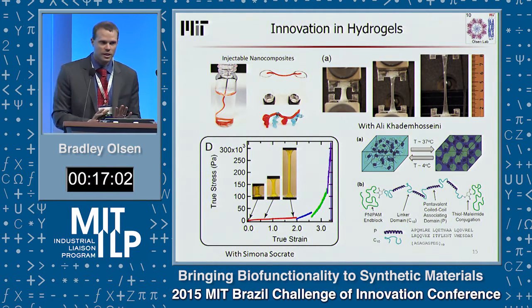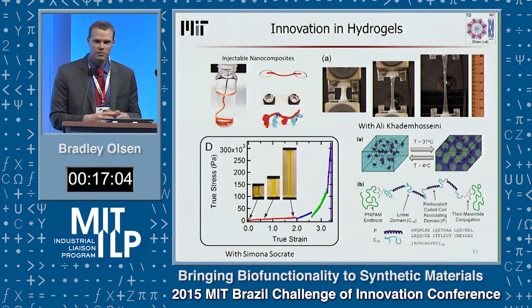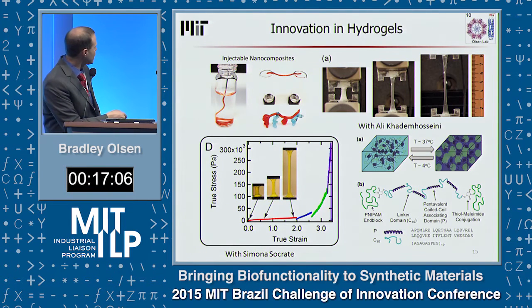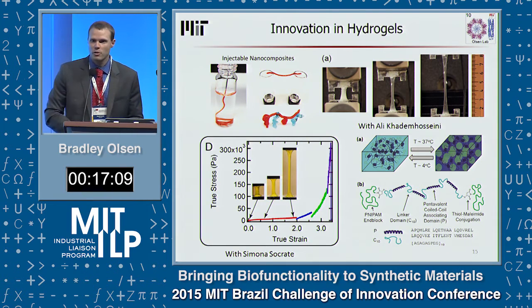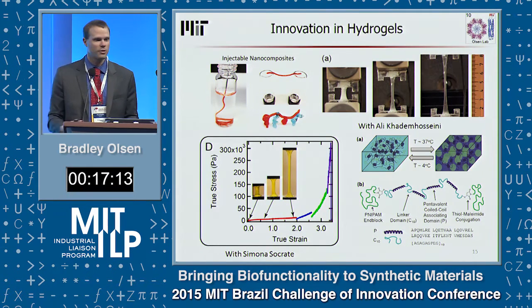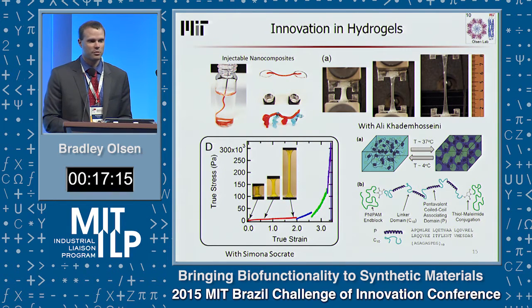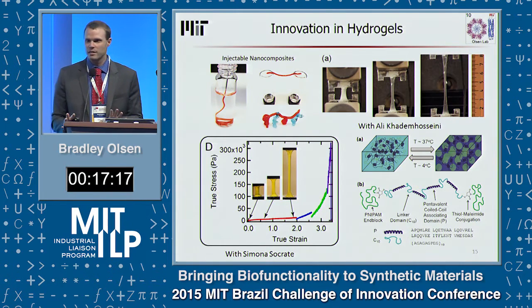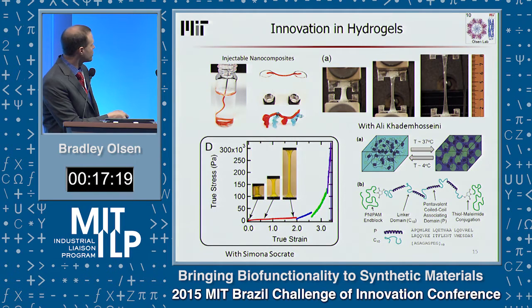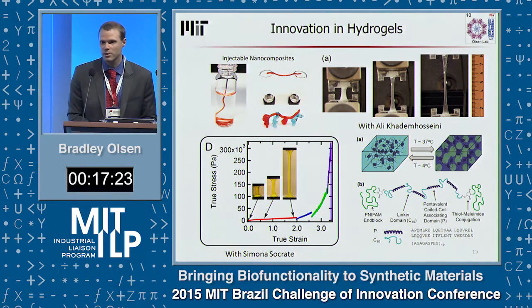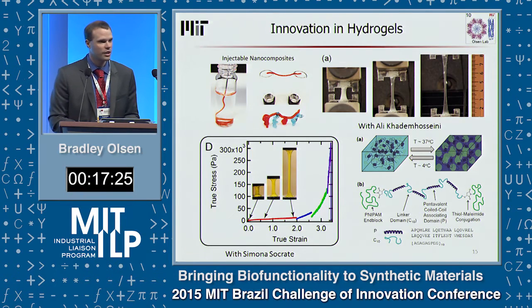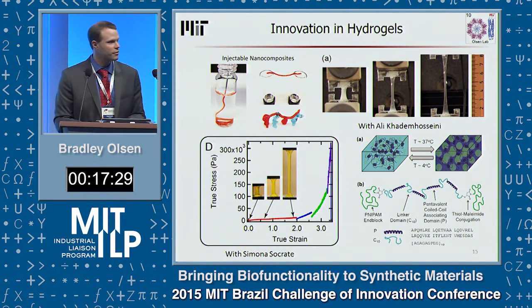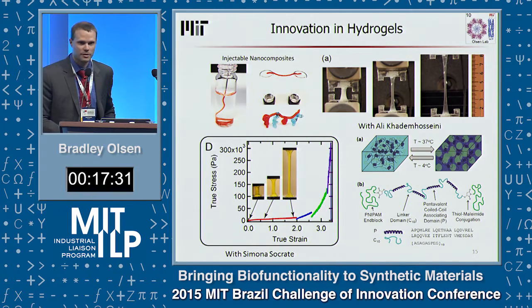And you can also look at developing these components to have new sorts of performance. Like this is a hydrogel that, as far as we know, is one of the most extensible hydrogels ever discovered. It can be stretched to 3,000% of its original length without breaking. And we look at making very, very tough hydrogel materials. So in this project, we can actually use copolymer self-assembly as a means to toughen hydrogels to resist cracking and breaking, and can make essentially tissue fillers and tougheners that have a very, very high strength.